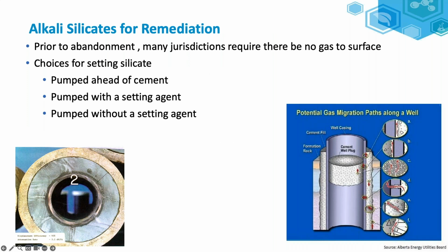I think we've seen the figure on the right quite a bit, so I'll gloss over that. Just lots of ways for gas to get out of the well. The fractures tend to be very, very small, and this is where we see a good fit for sodium silicate for blocking gas migration or surface casing vent flows. A lot of regulators require this.